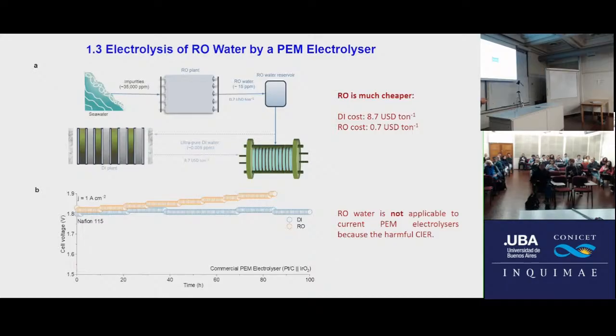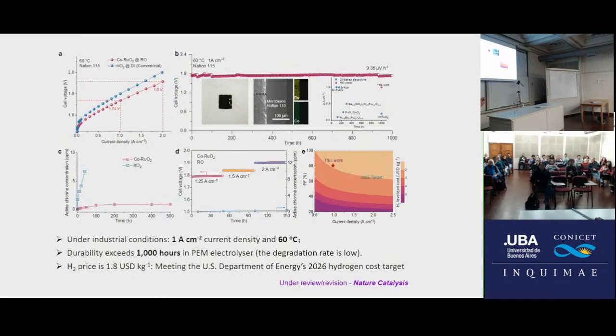This is my work. This is the first time in my research group to use RO water directly. Definitely we need to develop a new catalyst. This blue line is the commercial system: you can see the pure DI water and the very expensive catalyst. The red line is our catalyst, and we use RO water directly. We can run 1,000 hours. The degradation rate is very, very low. Compared with public results, our case is best.